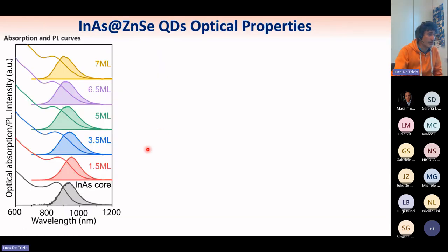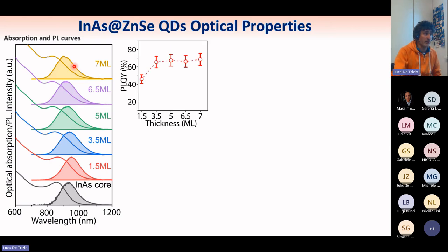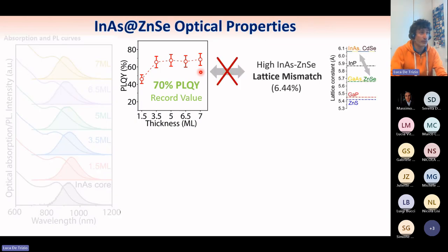And if we now check the optical properties, you can see that our dots absorb more or less at 800 something, 900, and they emit at 950 nanometers. So they emit in the near infrared region. And if we check the quantum yield, the efficiency of this emission, you can see that we reached values as high as 70%, which is extremely higher than the 10-15% reported so far. So we got a record value. And this record value is not really compatible with the high lattice mismatch between these two materials. So we were kind of surprised about this.